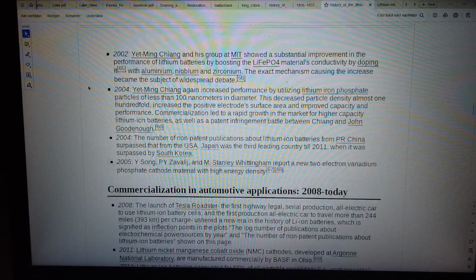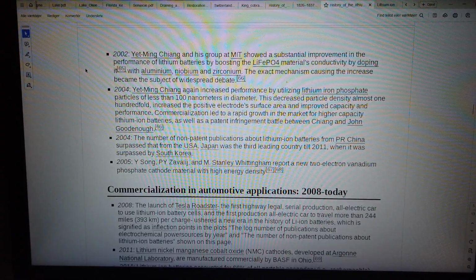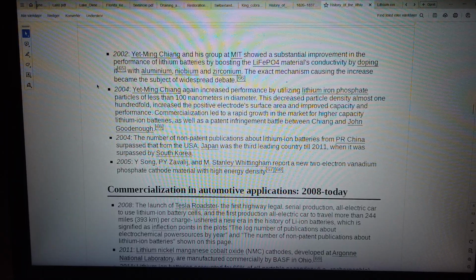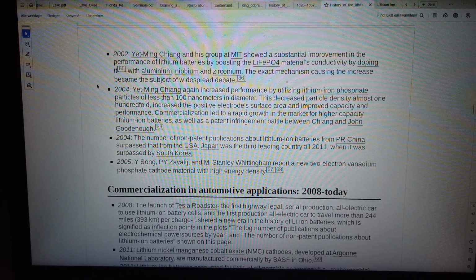In 2002, Yet-Ming Chiang and his group at MIT showed a substantial improvement in the performance of lithium batteries by boosting the LiFePO4 material's conductivity by doping it, 65, with aluminium, niobium and zirconium. The exact mechanism causing the increase became the subject of widespread debate. 66.